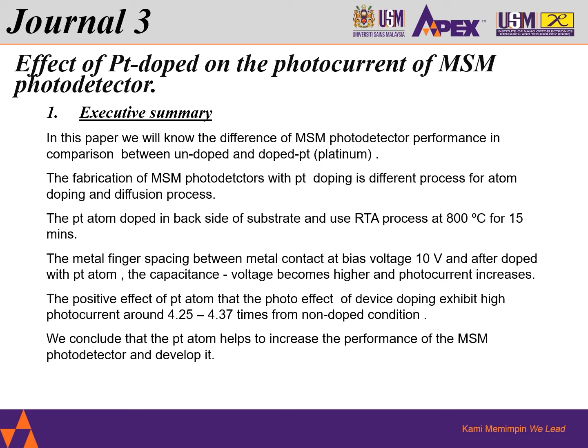The metal finger spacing between metal contacts at bias voltage 10 V, and after doped with Pt atom, the capacitance voltage becomes higher and photocurrent increases. The positive effect of Pt atom is that the photo effect of device doping exhibits high photocurrent, around 4.25 to 4.37 times from non-doped condition. We conclude that the Pt atom helps to increase the performance of the MSM photodetector and develop it.